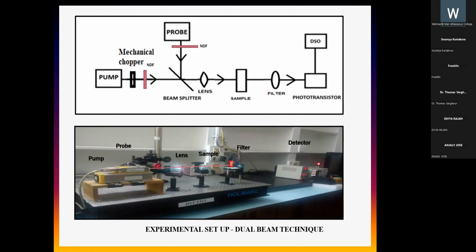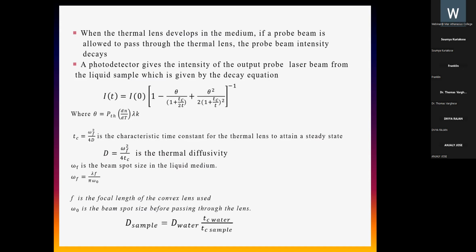Both pump and probe are made collinear in the mode matched configuration so that the beams propagate coaxially, which can create longer interaction length and better sensitivity. A mechanical chopper is used to modulate the pump beam intensity, and the changes in the probe beam intensity were monitored through a photodetector, which is connected to a DSO. The photodetector gives the intensity of the output probe laser beam, which is given by the decay equation given here. Thus, the time-dependent intensity is measured and fitted to get the intensity profile.